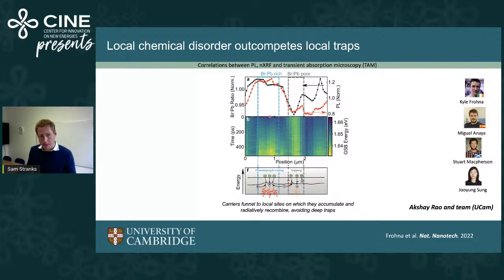When we look at this bromine-rich region, what we see is that the carriers start off at higher energy, and over time they funnel down to lower energy. This is what we're seeing essentially in real time: these carriers funneling onto these low-energy iodine-rich sites, on which they recombine very radiatively. So we can look at this as a section of what we propose is happening here. These regions with poor luminescence have lots of traps, and so this recombination is just what we would expect from a trapping region. But then these photoexcited holes are moving about, and we have very shallow energetic funnels that funnel these carriers onto low gap iodine-rich sites, on which they recombine radiatively with very high efficiency.